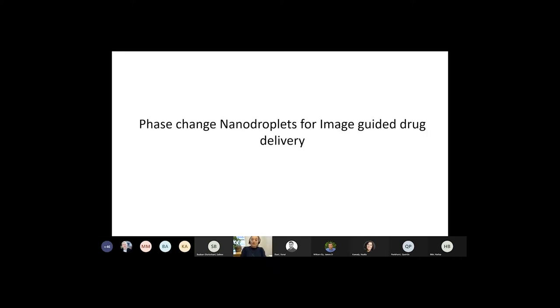Okay. So that was it with the thermosensitive nanoparticles, but the technology of ultrasound is exciting, and there are other materials in development that are very promising to be combined with focused ultrasound. Focused ultrasound is combined with bubbles at the moment, but bubbles have a very short half-life. So what we are doing, and some other groups, is trying to condense this bubble to a very small particle size, like nanodroplets, they are called. And these nanodroplets change phase. They have inside the core perfluorocarbon, a liquefied gas, surrounded by lipids. And when under the influence of low intensity ultrasound, these nanodroplets expand and become bubbles. Now, as bubbles, they are able to cavitate and